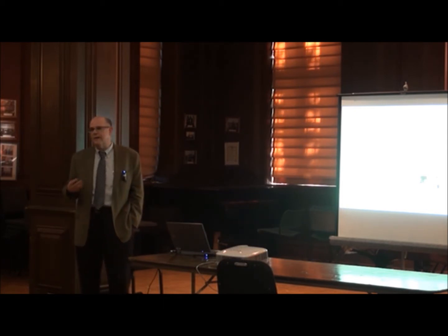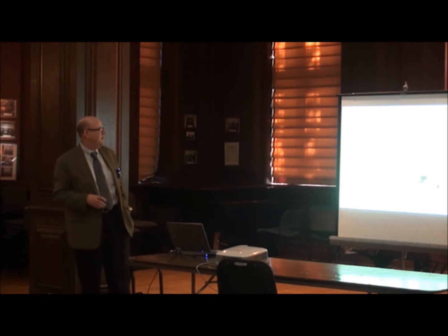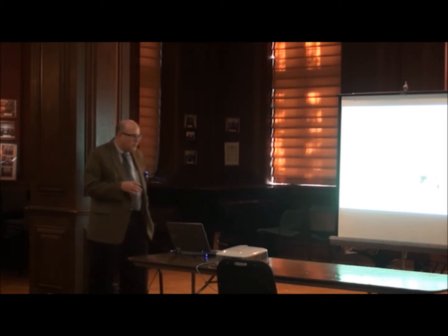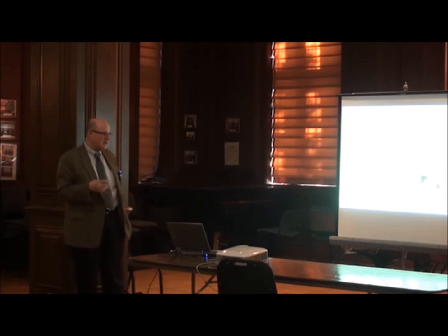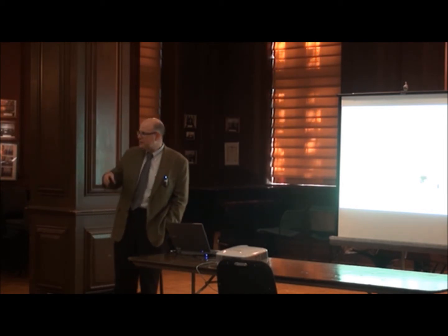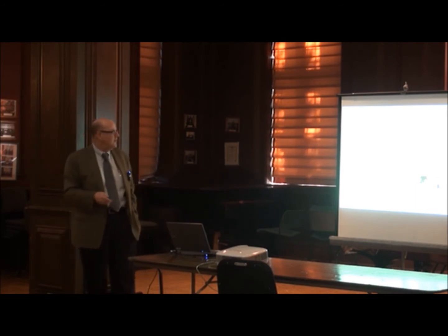So the bottom line is, what is the connection between surface texture and friction? Really, first order, it's the adhesion at the real area of contact. That's what we're talking about. There's also deformation of asperities and plowing of harder asperities and so forth. Other parameters also relate to this contact of the surfaces. As we know in the surface metrology world, surfaces aren't just a nice random distribution of little spherical-capped asperities. There are all kinds of distributions, and we have to be a little more aware of that.